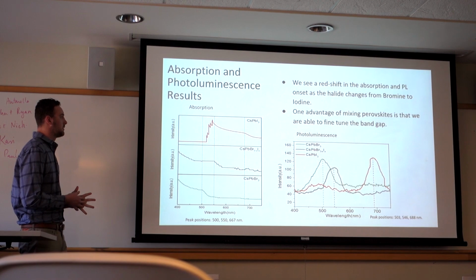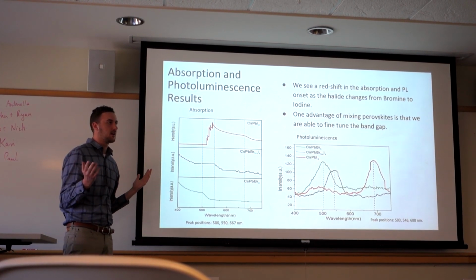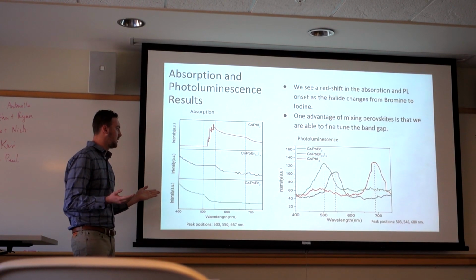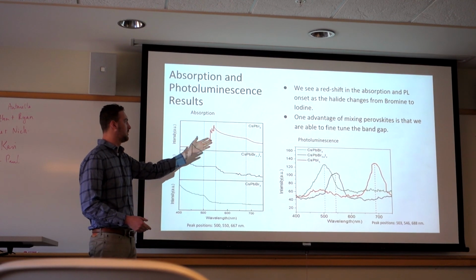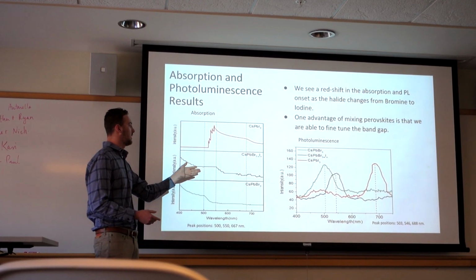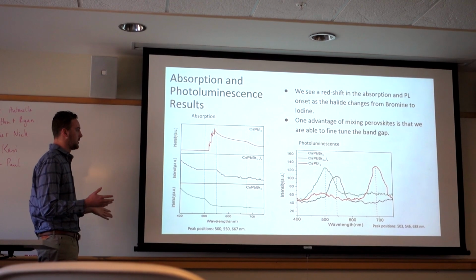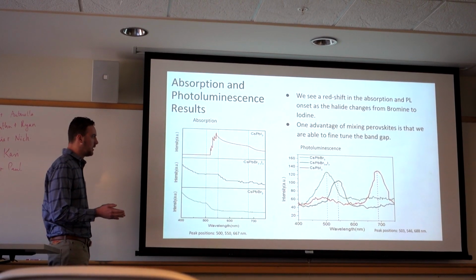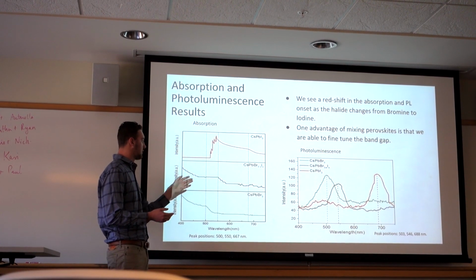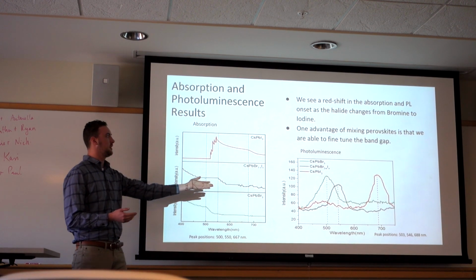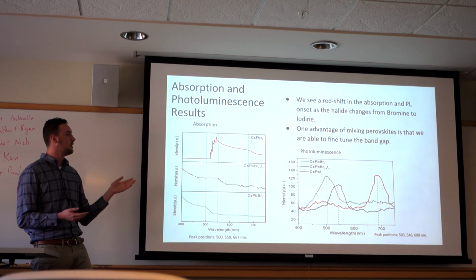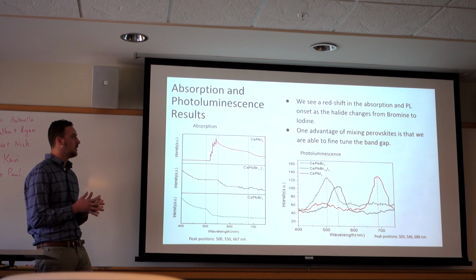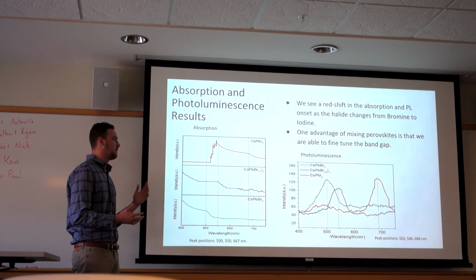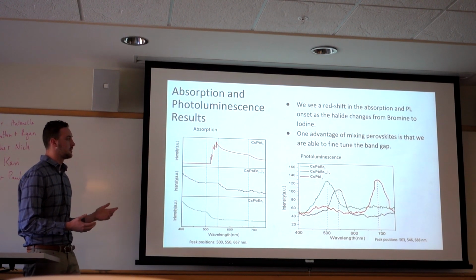And as you would expect from simply the colors of our inks, we see a redshift as we go from bromine to iodine, with the mixed perovskite falling somewhere in between the two. And note again that it's closer to bromine, as well as with the photoluminescence data. The photoluminescence peaks for the mixed perovskite fall closer to bromine.